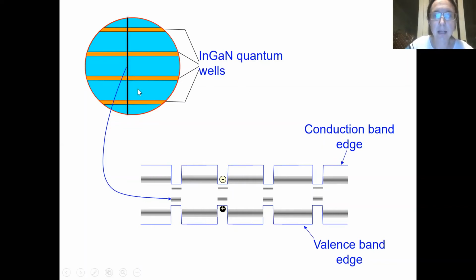So where that line passes through the crystal, it's passing through the quantum wells, it's passing through the gallium nitride layers between the quantum wells, and wherever it does that, it disrupts the perfect periodicity of the crystal. Now, band gap is all about periodicity. Band gap and periodicity are intimately related. So where we mess up that periodicity, we create extra states in the band gap, and the electron and hole can combine by the electron kind of trickling down through those states. We no longer have a forbidden gap. We've got places in the gap for the electron to sit, and as it wanders from extra state to extra state, it gives out not light, but heat. And we don't want our LED getting hot because that's energy that we were hoping to use to light up the room that we're wasting as heat.